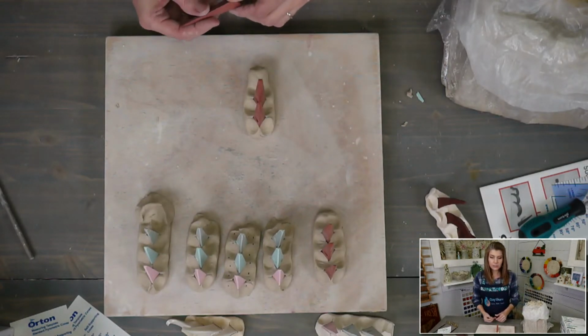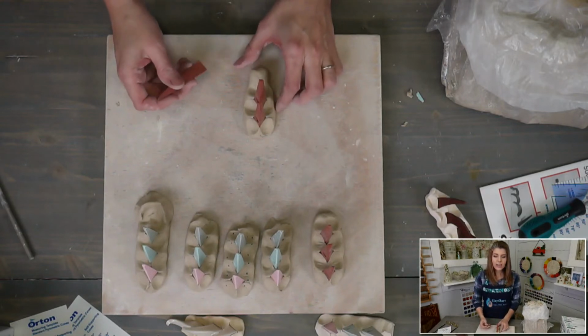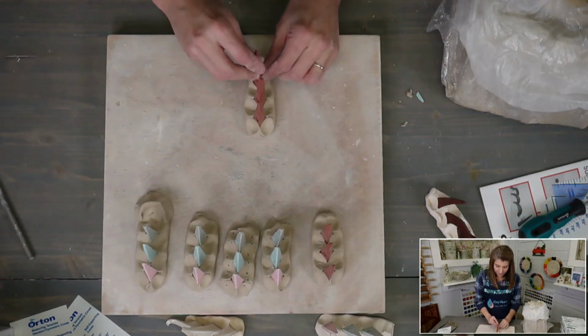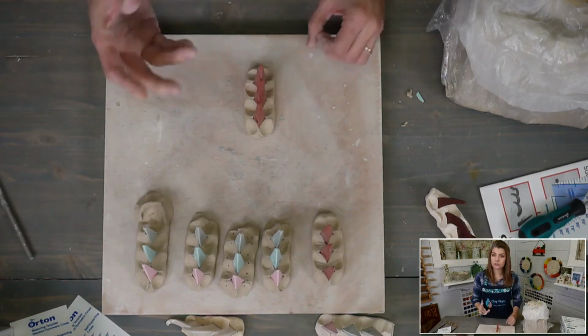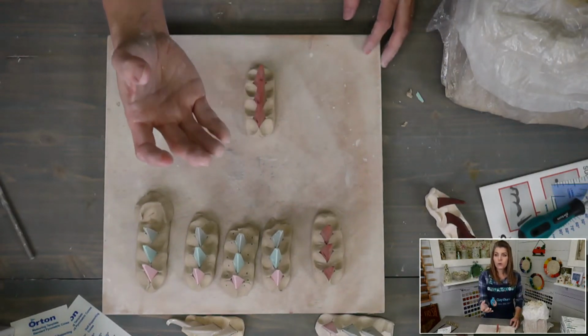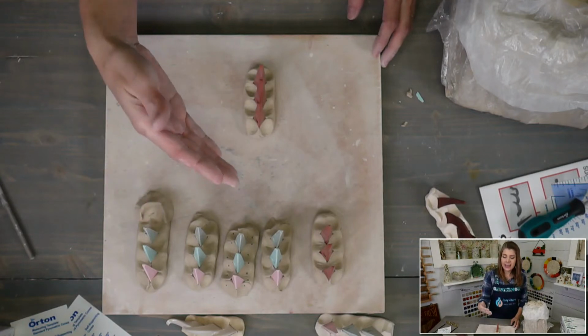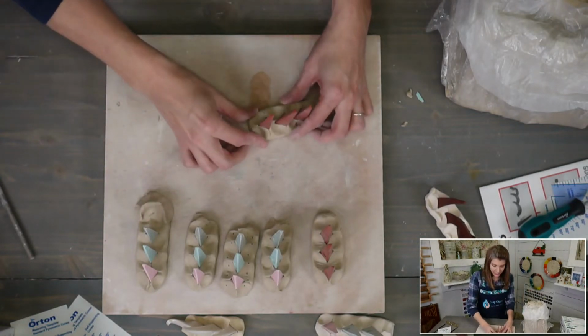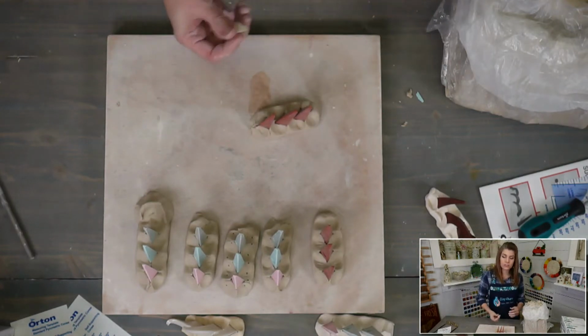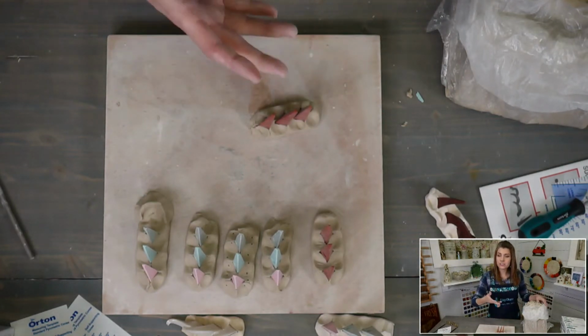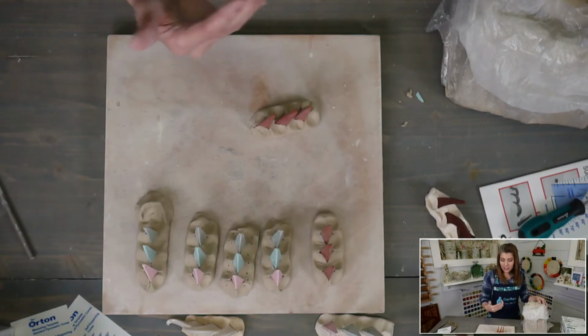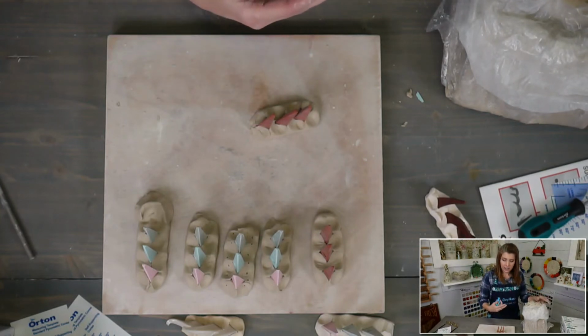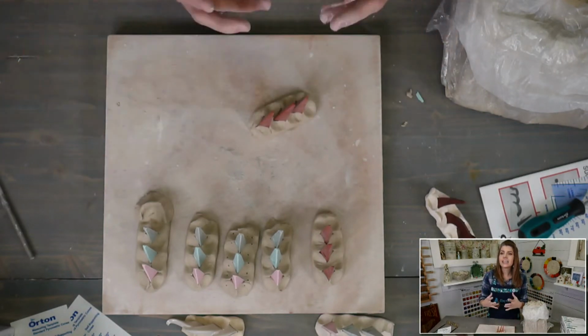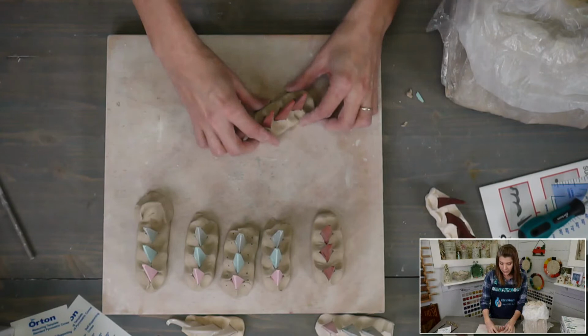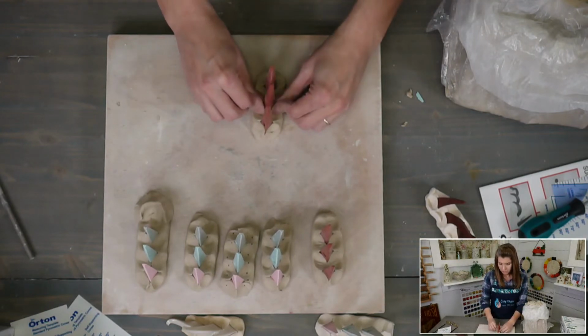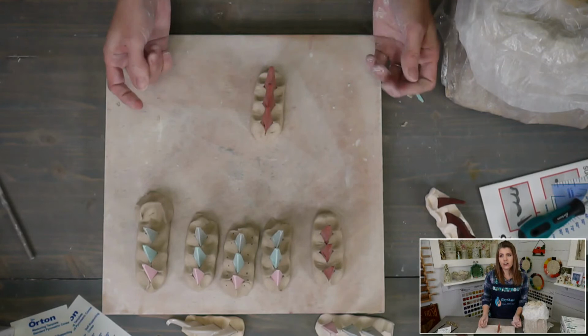So what happens to the clay when you bisque fire to cone 03? Catherine, if it is a cone 5 clay, what can happen is the clay can start to vitrify. It can start to close up, so it won't be as porous as it would be normally. And then when you apply your glaze, it won't be as absorbent, so you'll have a difficult time for the glaze to soak into the clay. You might not get as even of a glaze application. It might be a little thin looking because the clay can't actually pull that glaze in. So that's what can happen. Will it hurt your piece? No, not really. It just might affect how the glaze applies.